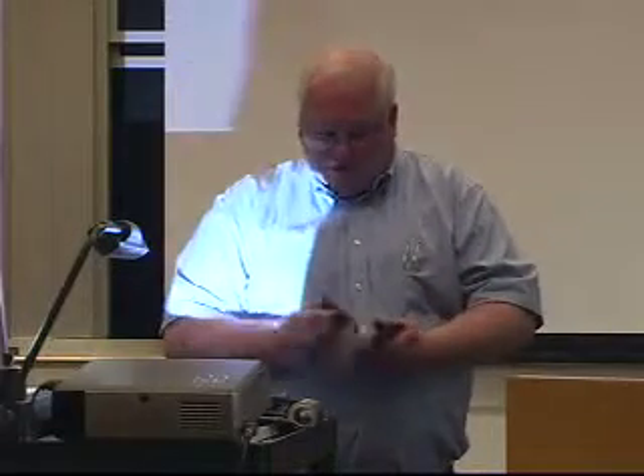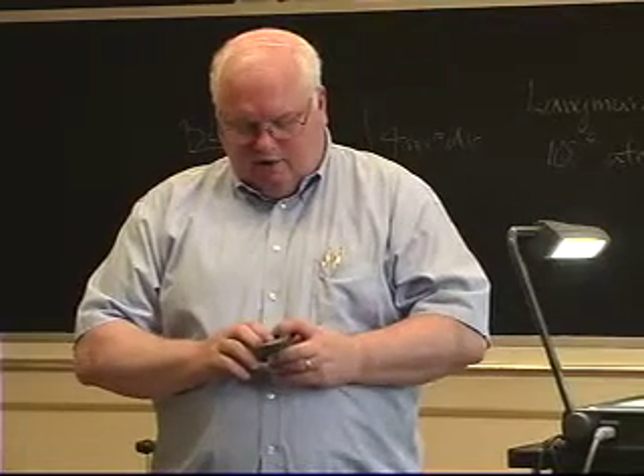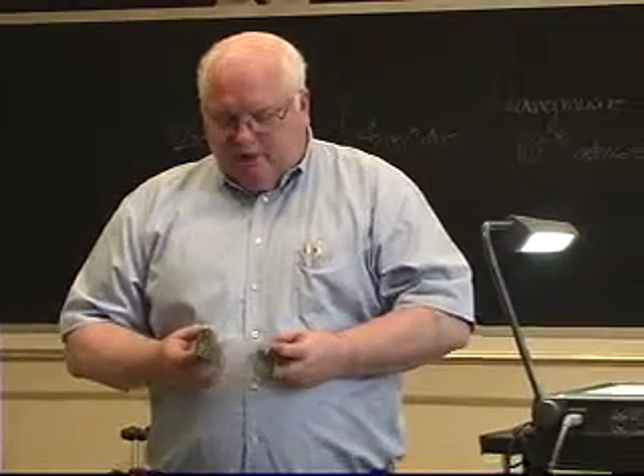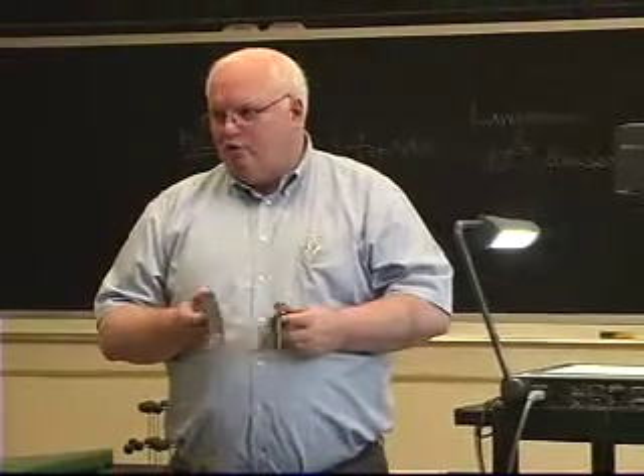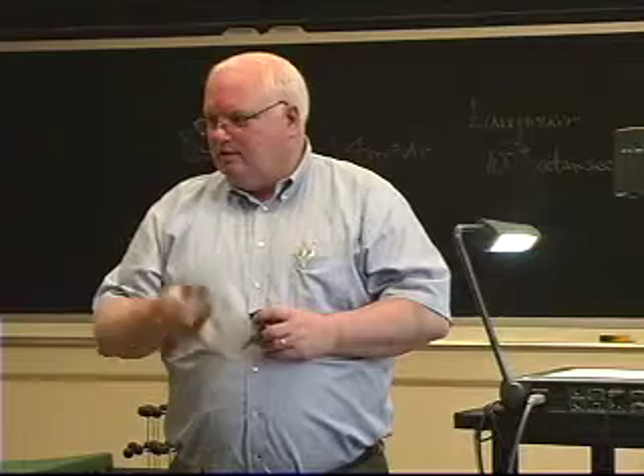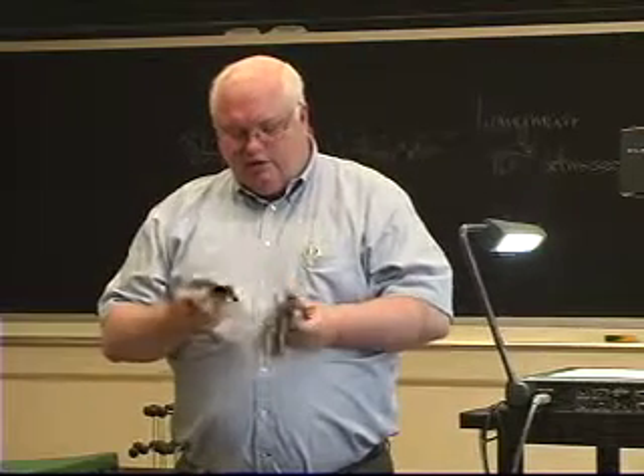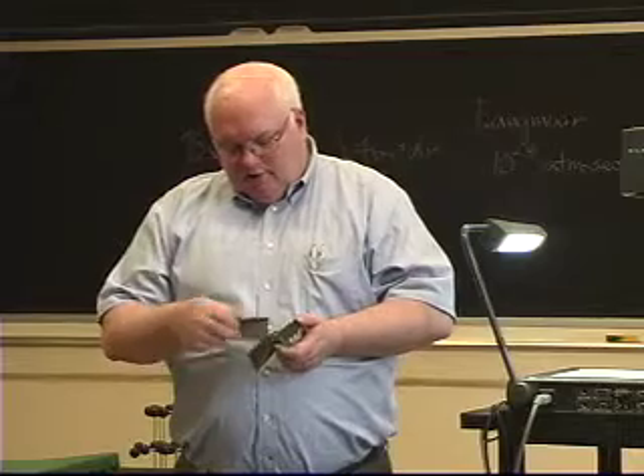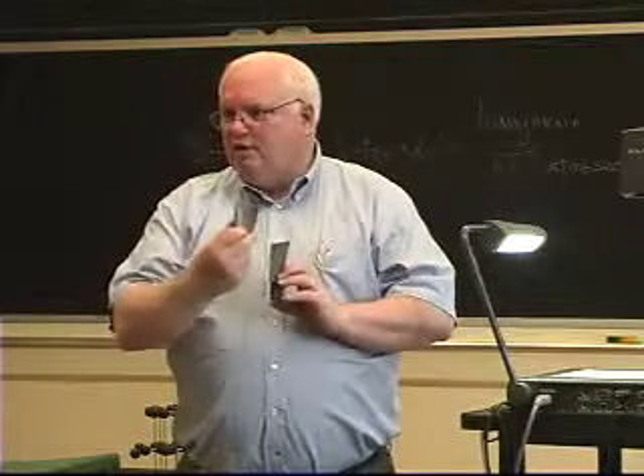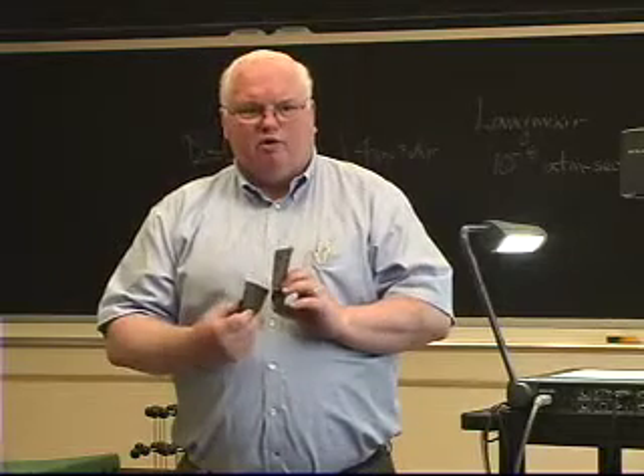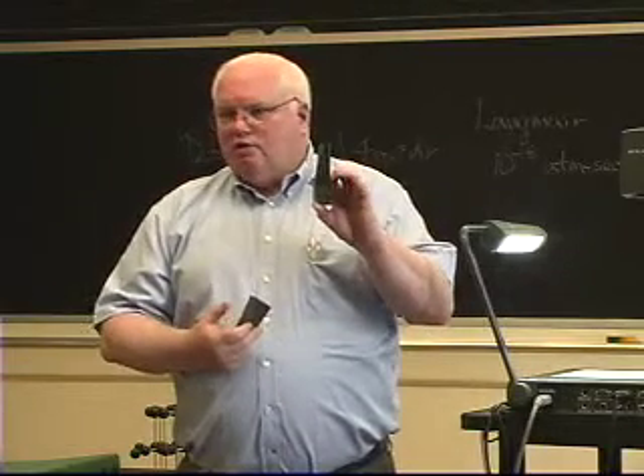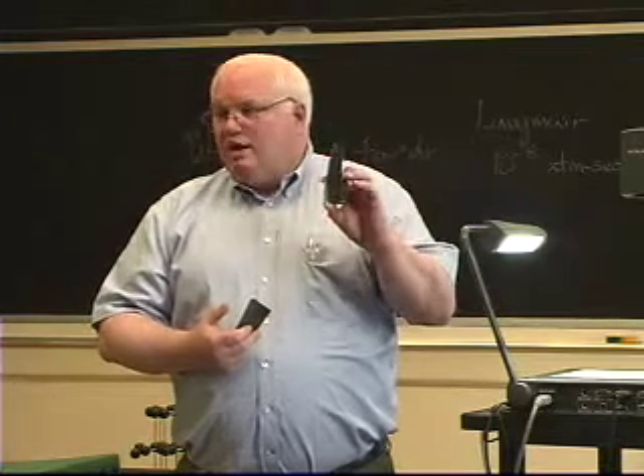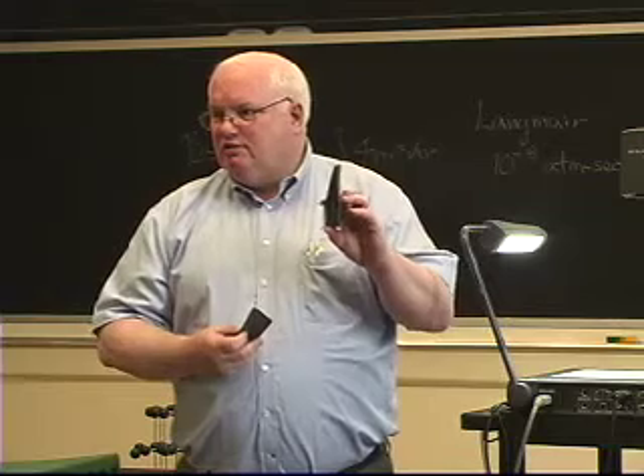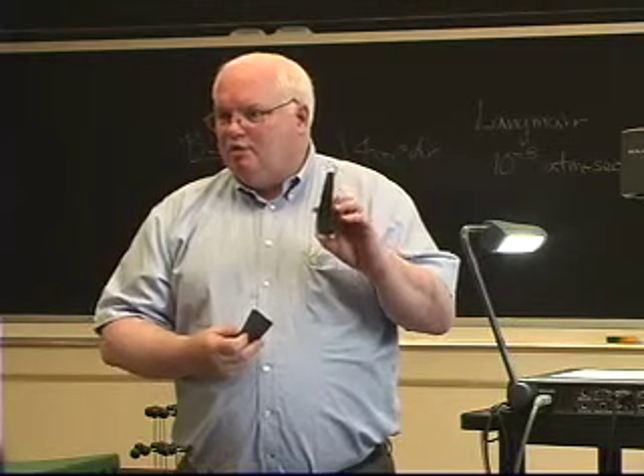So I could pass this one around. Actually, I might as well pass this one around. This one is actually a single crystal blade. This is kind of from a 30-year-old type of aircraft. They get fancier now. If this was a new blade, it was good, it would be worth $4,000. And there's 100 of them on the disc. Okay. Now this one was grown as a single crystal. It's got a ceramic core, and it has all these turbulations inside because they blow air through it to cool it. Because the turbine operates, the melting temperature of this alloy is around 2,400 degrees Fahrenheit, and they run it in a gas at 3,000 degrees Fahrenheit. So if you lost your cooling air, you would melt your engine.